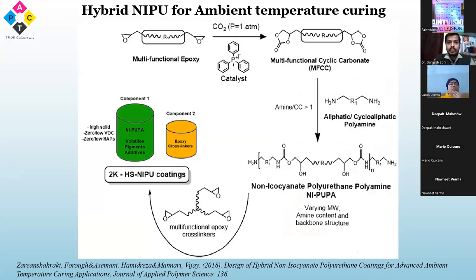This is another example of room temperature curable coatings in which multifunctional epoxy is again converted into multifunctional cyclic carbonate. And after reacting with aliphatic and cycloaliphatic polyamine, polyurethane can be obtained, which is terminated by amine groups. And once the amine terminated polymer is obtained, we are very familiar with epoxy amine systems, which are used very commonly. So this again forms an epoxy amine system, which can be cured with multifunctional epoxy groups. After the reaction of this amine and epoxy group, we can obtain two component high solid non-isocyanate polyurethane coatings, which are curable at room temperature.